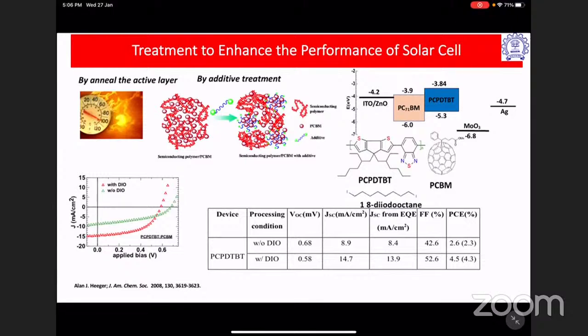In terms of the fill factor, on the third column, the JSC, if you look at the table, you have the fill factor going from 42% to 52%, and also short circuit current density going from 8.9 to 14.7 by adding the DIO additive. DIO is basically diiodooctane. It's a high boiling point solvent, which allows the polymer chains to optimize the morphology over time.